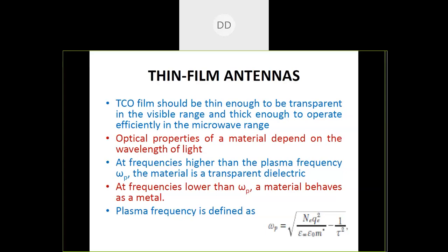So there is a concept of plasma frequency. A material is a transparent dielectric for frequencies higher than the plasma frequency, and similarly, at frequencies lower than the plasma frequency, a material behaves as a metal. Using this plasma frequency relation, we can check the different characteristics. This plasma frequency again depends upon the electron concentration. So we can change the electron concentration, and somewhat change the plasma frequency, and we can design our material as per the required frequency range.